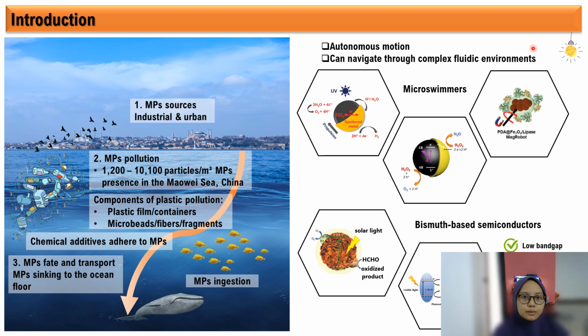This study proposed to degrade submicron-sized microplastics via microswimmers. Microswimmers are micron-sized machines that have autonomous motion that can be activated through light activation, fuel activation, and external magnetic force. In this study, bismuth-based microswimmers are desirable since they have a low band gap, excellent chemical stability, non-toxicity, abundance, and low cost. Moreover, bismuth has been used widely in pollutant degradation such as formaldehyde and phenol.